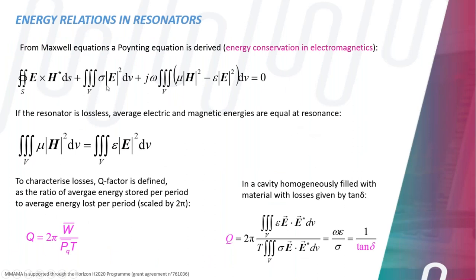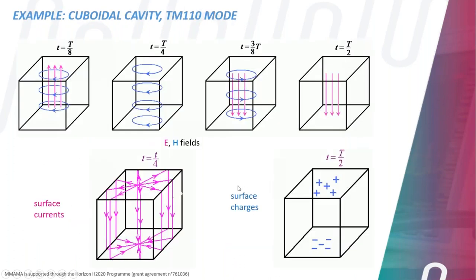About losses, that's a little bit of manipulation with the Maxwell equations, and we see that in a low loss case, the electric and magnetic energies in the structure are practically equal. And we define the Q factor, which tells us how much energy is dissipated per period versus how much energy is stored in the structure. When the resonator is fully filled with a material, this will be the inverse of the material loss tangent, the parameter we are looking at.